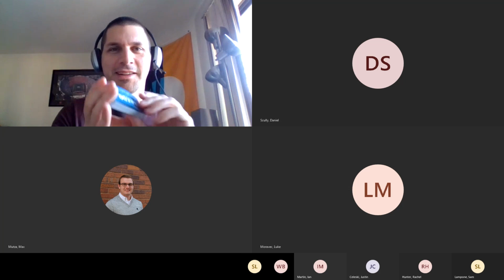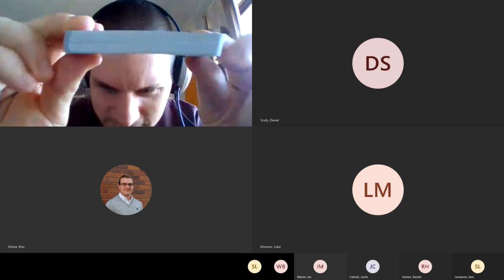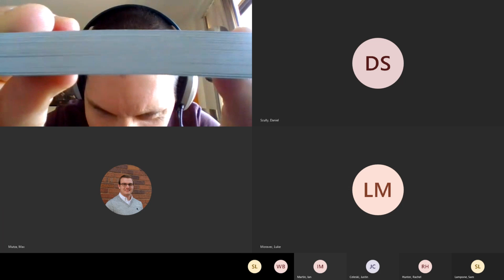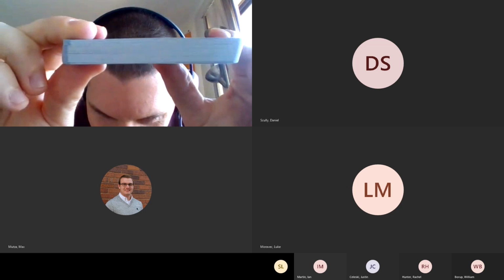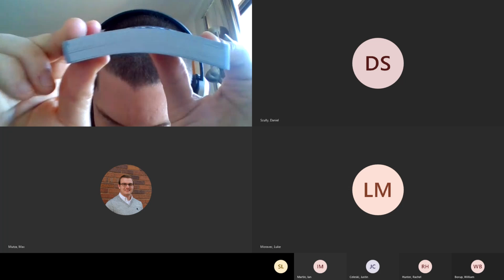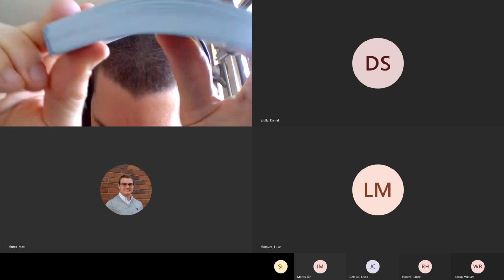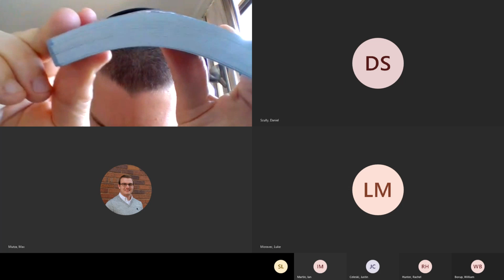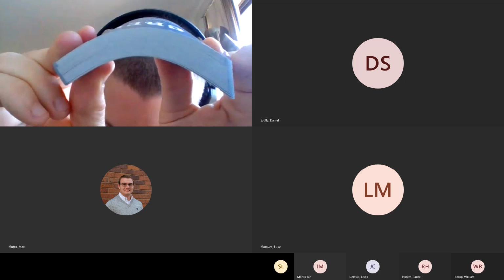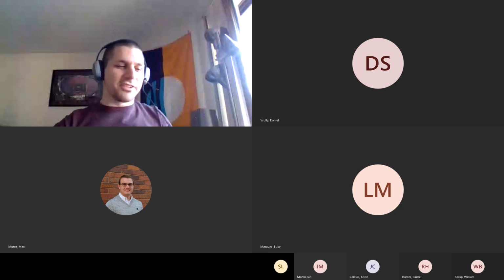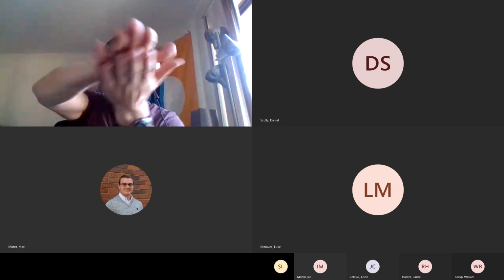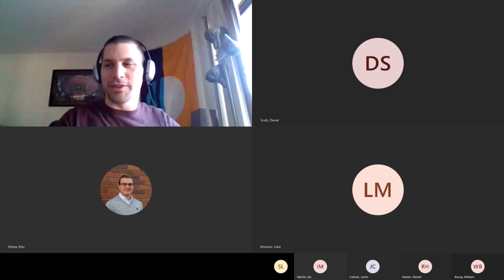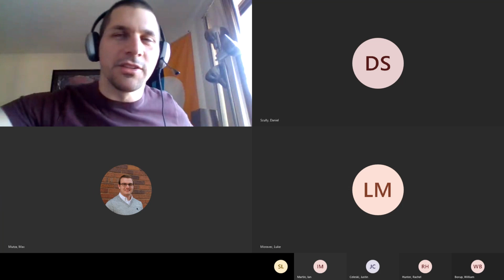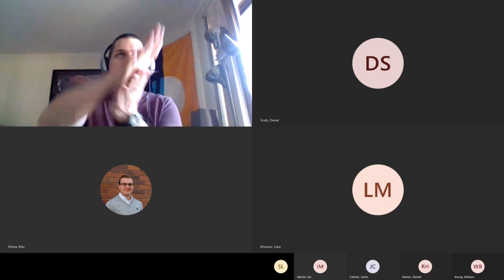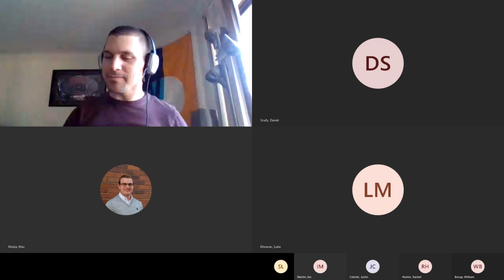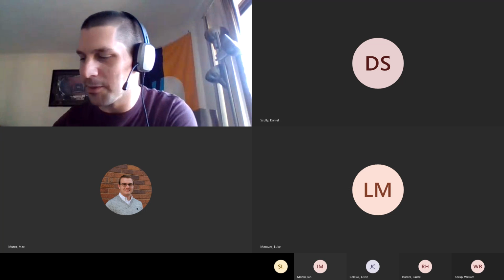Props. All right. So this is a stack of cards, right? The idea here is that if I put this thing into a 3-point bend, which I'm going to do right now, each one of those layers is like sliding against each other. Okay, might be a little bit difficult to see, but hopefully we can see that. Those layers sliding against each other is the mode 2 type of failure that we're looking to achieve. So what's happening here is that this sliding shearing mode is activating, especially at the midplane.